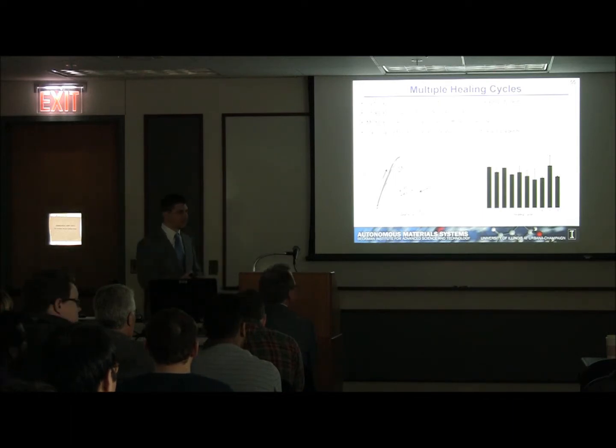So yeah, sorry if this was unclear, but when we bring the sample back together the first time and heal it the first time, the air purge is done immediately after we deliver the healing agents. So the channels are kept clear by keeping the air pressure on the channels throughout the duration of the healing cycle. So that's what keeps them clear. And so the healing agents are in liquid form immediately when we deliver the air, so that's how they can migrate into this multiple healing agent. Okay. So the healing agent that you're saying is coming out is because of this air escaping while the healing agent is still in the liquid form, which makes it little. Yeah.